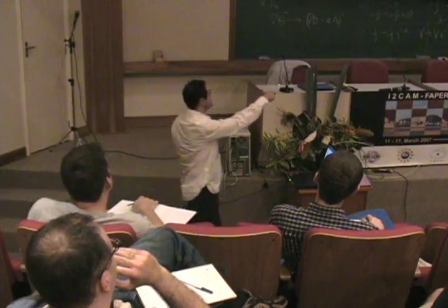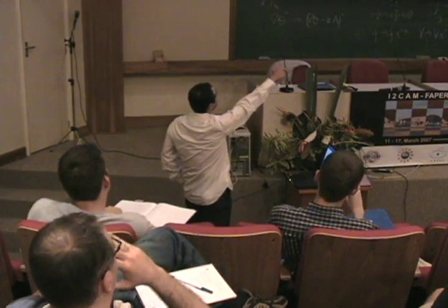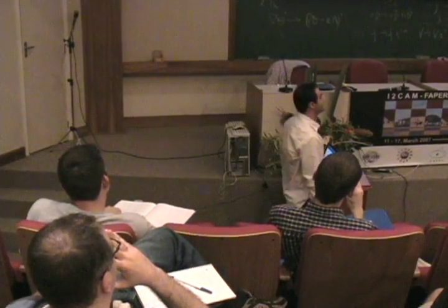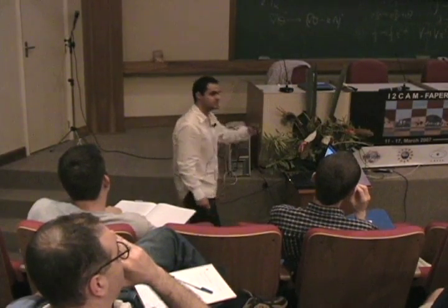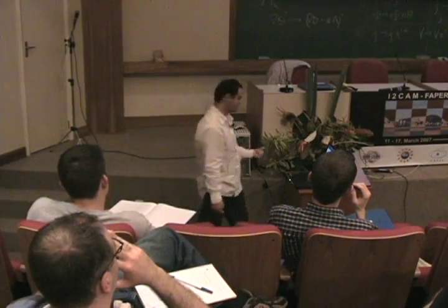That's measured by muon spin rotation. And if you go to the cobalt side, you do find superconductivity in Ce2CoIn8. But it has a T_c at 1 Kelvin, which is a factor of 2 lower than the CeCoIn5.